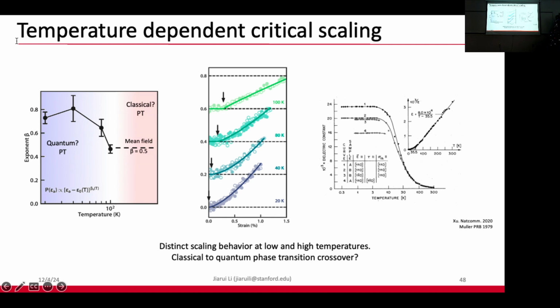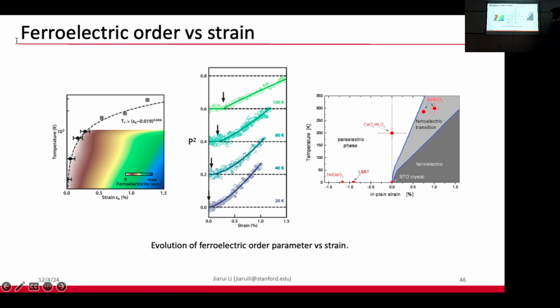And this is also consistent with a measurement taken decades ago in single crystal strontium titanate, where at high temperatures, when you measure the dielectric constant, the inverse of the dielectric constant follows the Curie-Weiss law very nicely until it goes below around 100 Kelvin, and it deviates, suggesting that when you suppress the thermal fluctuations, the quantum fluctuations get prominent, and the system enters a quantum regime rather than a classical regime. So we believe that we're demonstrating a crossover from a classical phase transition to a quantum phase transition regime in this strain-temperature phase diagram.